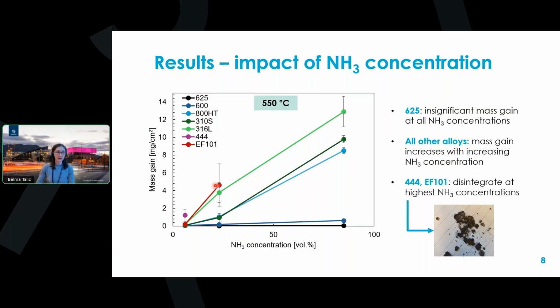And for these ferritic steels, 444 and EF101, we observed that at the highest ammonia concentration, the alloy coupon was completely disintegrated after the 200 hours of exposure. This is why we don't have any points here at the highest concentrations.